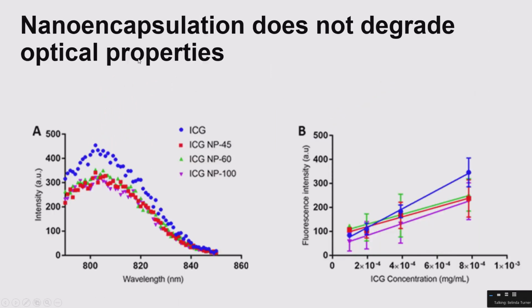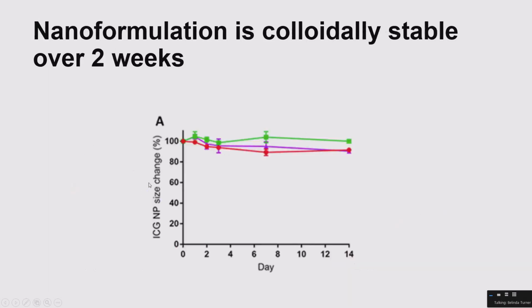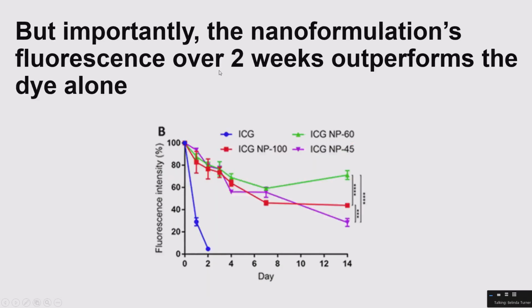So our nano encapsulation does not degrade the optical properties of the ICG. So you can see the blue lines are the ICG, nanoparticles below on par. And importantly, the nano formulation is colloidally stable over 2 weeks. So we measured the size over 2 weeks, and there was not really a change in the size over that period. But importantly, the nano formulation's fluorescence over this time outperforms the dye alone. So as you can see, the clinically available ICG dye crashes out at 2 days, and our nanoparticles had signal still at 14 days.